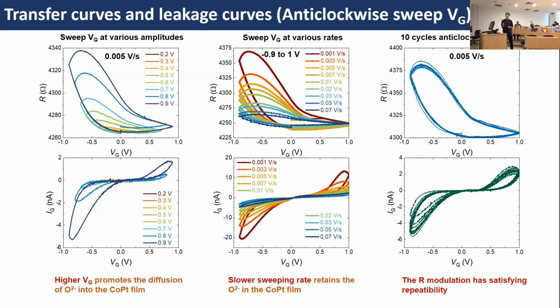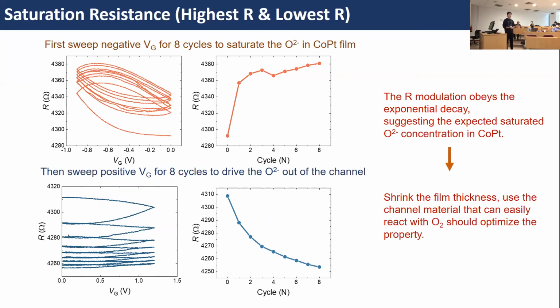And then we try to sweep at different sweeping rates. Here we can find that at the lowest sweeping rate, we get the highest modulation rate. And then we want to make sure that this device has good repeatability, so we sweep the gate voltage for 10 cycles. You can see here that nearly all the loops overlap with each other. However, for the insertion of the oxygen ions, there is a limitation. The limitation is that we cannot apply a high voltage because it will destroy our device. Also, we want to make the device as thin as possible so that the oxygen can be uniformly doped into the thin film. In this way, it can get the highest modulation rate.